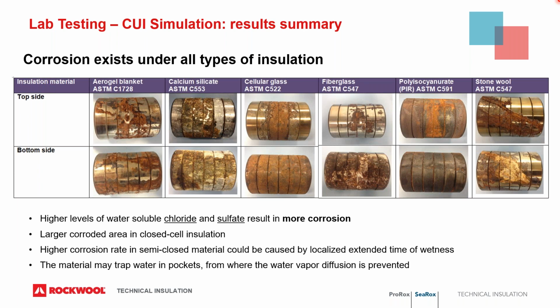The insulations that leached out higher levels of chloride and sulfate resulted in more corrosion. Larger areas of corrosion are found under closed cell insulations versus open cell insulations. That'd be a good question for someone if you don't know the difference between closed cell and open cell. This directly corresponds to NACE's statement on drying out the fastest. With closed cell materials like PIR and cellular glass, water had a hard time escaping, whereas open cell material allowed for that vapor to escape from the pipe surface through the insulation, thus lowering the time of wetness.